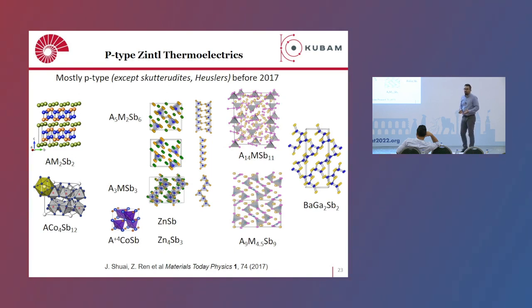Most of these materials inherently show p-type properties. So 122, 526, 313, 14-1-11, 122 inherently show p-type behavior because of cation vacancies. Generally, when you make them, you observe a very stable defect in the structure, which is a cationic defect, calcium, magnesium, or whatever. They show inherently p-type behavior.